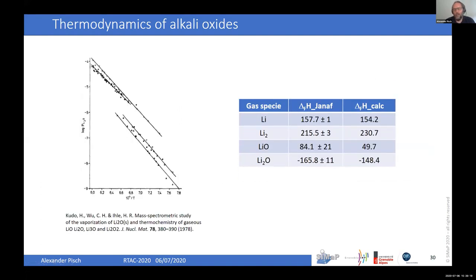Another interesting feature of the calculation is that you can also calculate the gas species. And I did that again with the SCAN functional for the gas species. And you see the agreement is not bad. For pure lithium, we basically find the same value that you get in the Janaf compilation. For lithium oxide, at least we have the right tendency. We found 50 and the experimental value was 84 plus minus 21. So the error bar is pretty large. And for Li2O, the value is rather negative. And again, we find the right tendency. So I think the proposed method may also be a good way to check gas data if you find them in the literature, in order to see if the order of magnitude is correct.